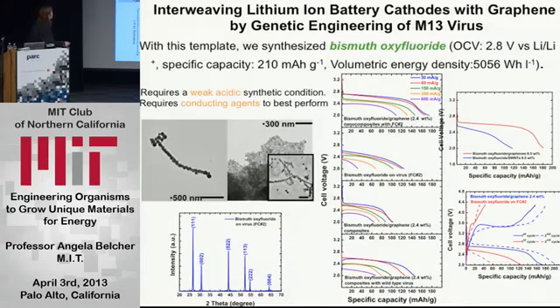And there's a lot of data. Sorry about that. This is volumetric energy density here. But basically, what we found is that we compared them to carbon nanotubes, and the ones that bound the graphene were better than binding the carbon nanotube, so it was a good choice.